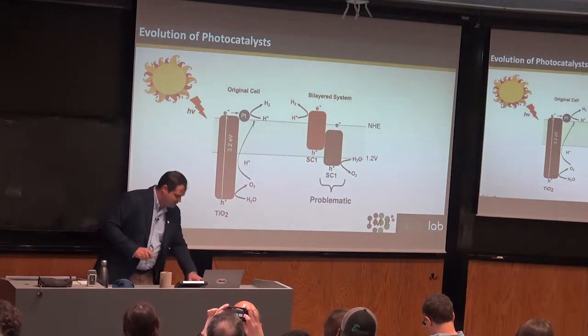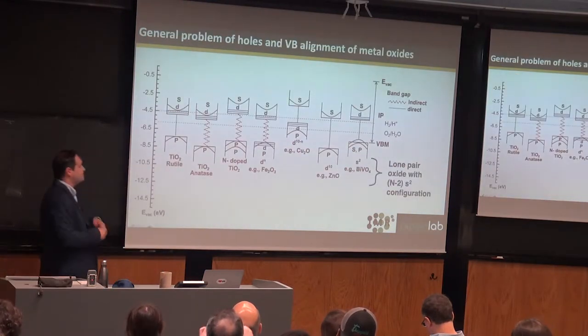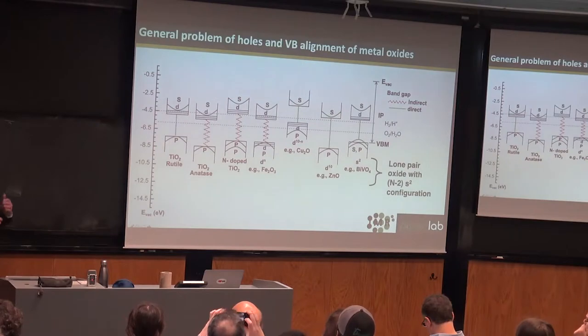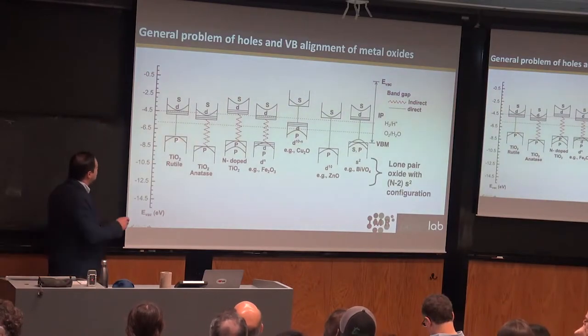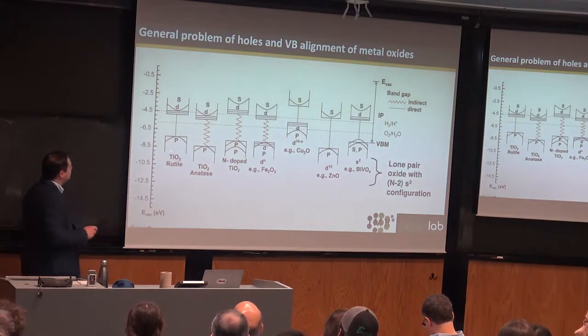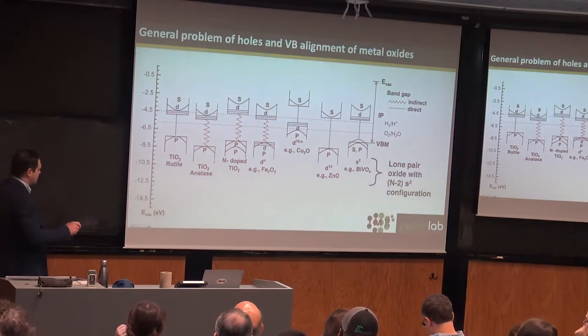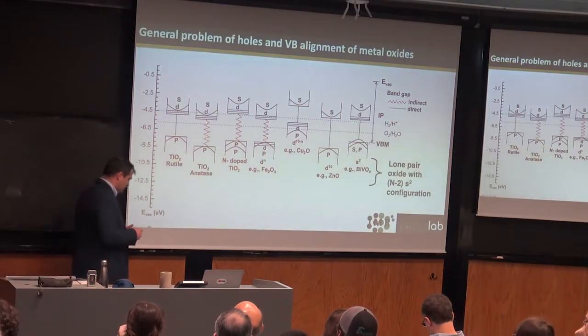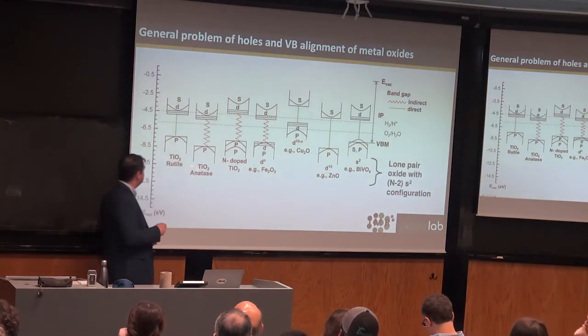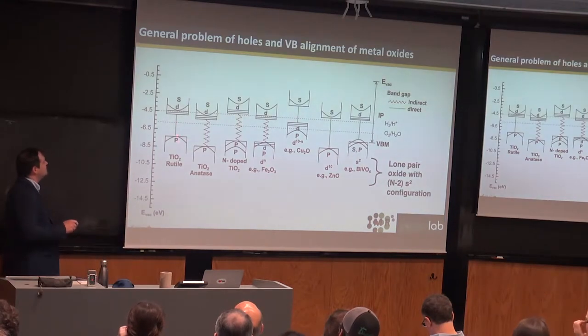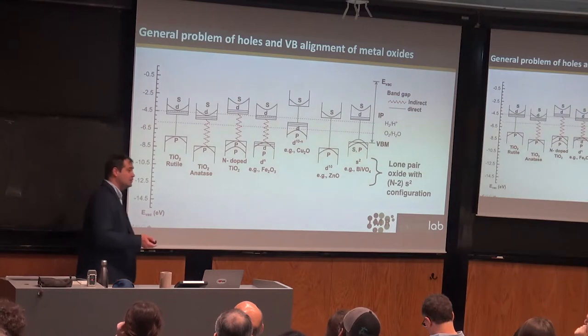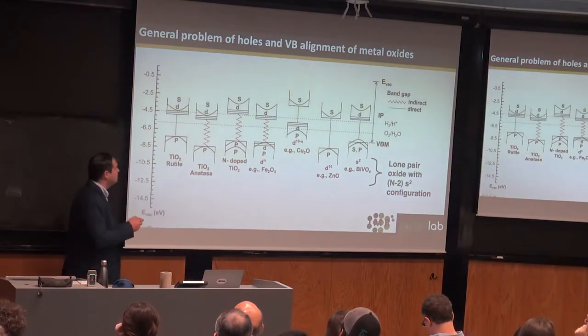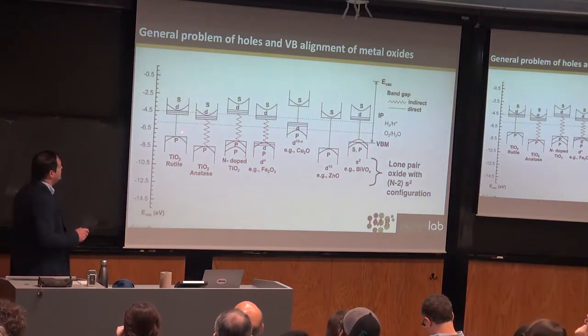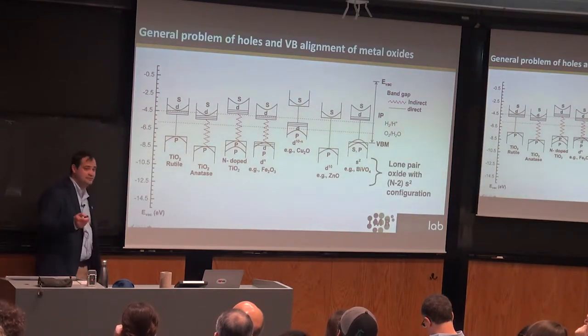The reason why this one is the problem is because they're metal oxides. Okay, so metal oxides, if we consider our TiO2, the idea is that you have these very strong, you're filling your oxygen 2p states, they like to be nice and stable, they're deep compared to the vacuum level, which means they're deep compared to the normal hydrogen electrode, if you're a chemist. And the idea with this is we are basically wanting to oxidize oxygen.